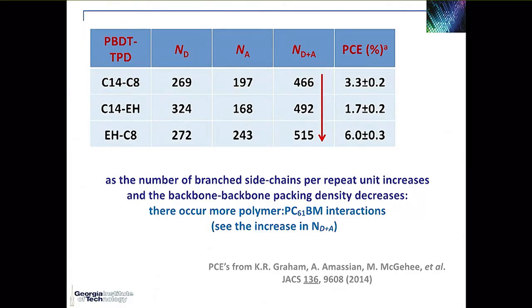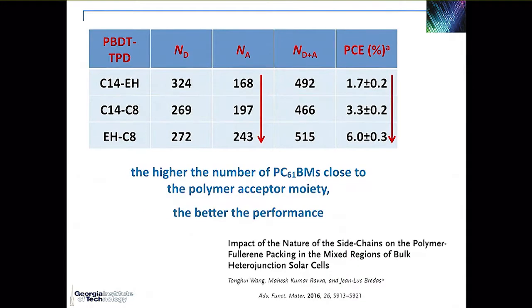And with respect to the power conversion efficiency that you get in the solar cell, the best correlation that you find is with the number of fullerenes actually interacting with the acceptor, the electron poor part of the polymer chains. So you get a correlation between the number of fullerenes interacting with the acceptor part and the PCE.